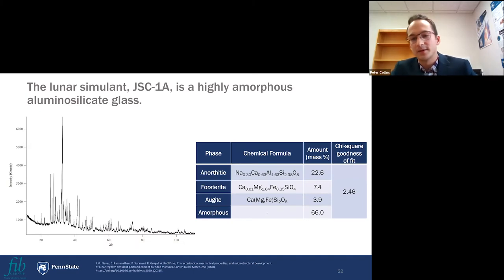I mentioned that some of our samples were ordinary Portland cement and contained a lunar simulant. A colleague of mine and my advisor worked on characterizing the mechanical properties and microstructural development of an ordinary Portland cement that had a lunar simulant. In this case, the lunar simulant is JSC-1A, and it's a highly amorphous aluminosilicate glass. You can see that it's 66% amorphous, and its composition is similar to what you'd see in a class F fly ash. And we'll talk about that in a little bit more detail in a minute.